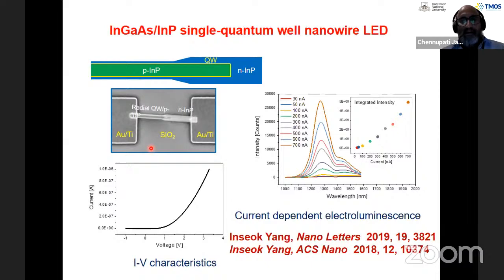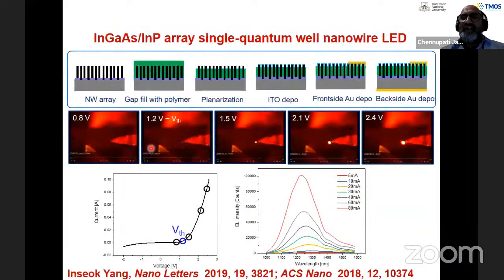Okay. So now, of course, instead of using single nanowires, before finishing his PhD, Insuk again tried to make nanowire arrays. So these nanowires are grown vertically, and he fills this with a polymer material. He selectively etches this polymer using plasma etching, exposes the tips of the nanowires, puts some indium tin oxide on the top, and puts some metal contact at the top and the bottom, and then he injects current and looks at the light emission.